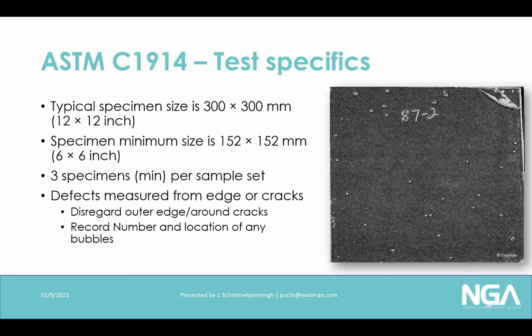test. What it looks like is it's typically run on either a 12x12 or a minimum size of a 6x6. You do 3 specimens per test. That means you would put 3 specimens from the same run or from the same laminate into the boiling water, take it out 2 hours later, or put it in the oven and take it out 16 hours later. The defects are measured from the edges or the cracks, and the defects in this case tend to be bubbles. And you can see on the right-hand side a picture of a laminate that has clearly failed this test, and you can see all of the little bubbles that are forming.